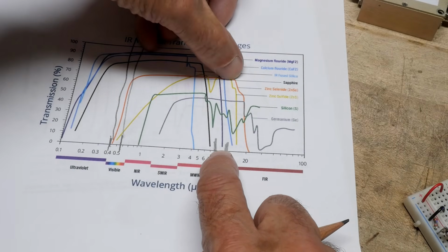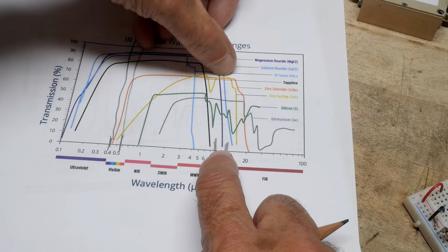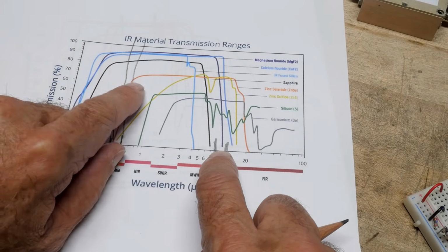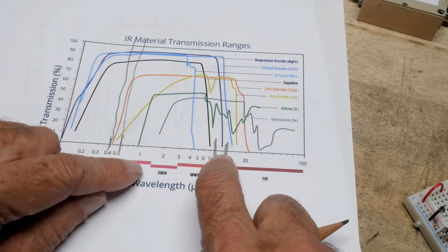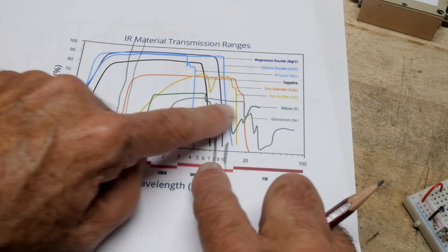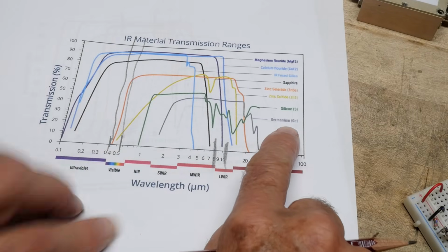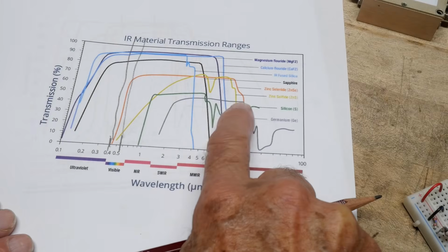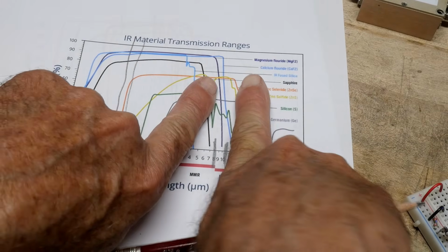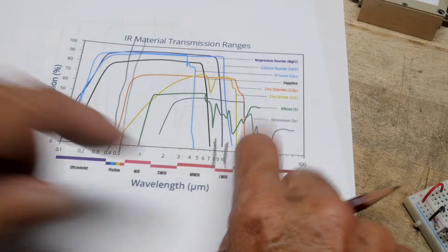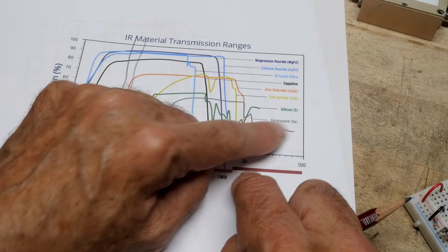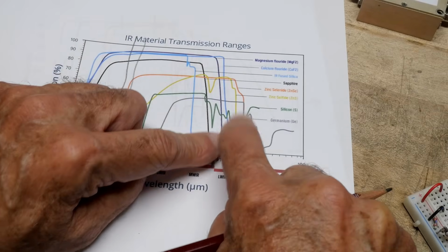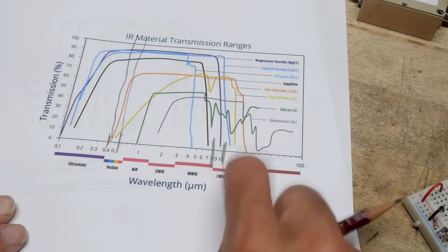They're kind of steep. Maybe this one's a good one. We can use that, the orange one. That's zinc selenide. Yeah, zinc selenide is really good there, okay? But it's only about 70% transmission. Okay, here's another one. Here's another flat one there. What is that one? Hey, guess what? Germanium. So germanium's good, but it's only about 50% transparent, but it's nice and passes all of those wavelengths. So really the only choices here are zinc selenide, zinc sulfide, and germanium. So silicon doesn't work. Silicon's kind of there also. So really we only have a couple choices here.